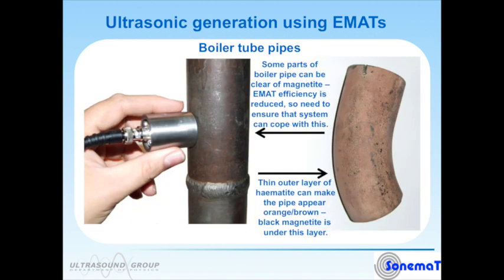The slide we can see here is a handheld shear wave EMAT being used on a couple of boiler tubes. The pipe on the left has a more black coloured surface layer. The pipe on the right looks a little bit more red to orange. The red or orange colour here is a thin layer of hematite on top of a much thicker magnetite layer. This could be easily removed, and what we would see is an exposed black, shiny, hard oxide layer.